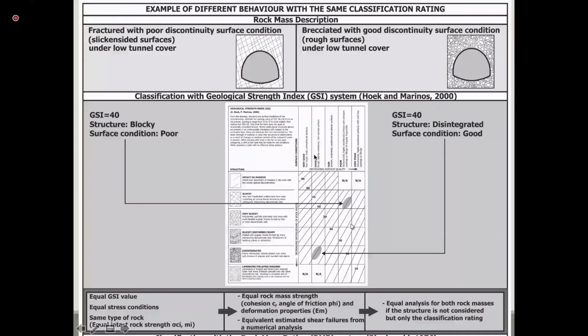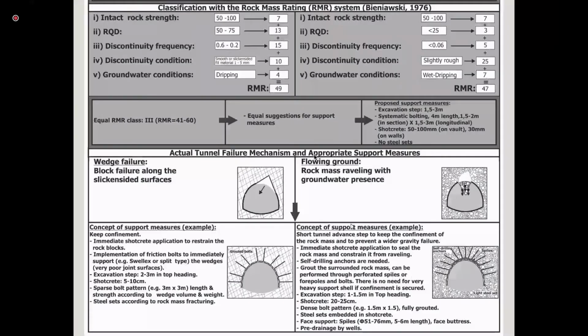If you do that, if you go and calculate your properties by the Hoek and Brown failure criterion, you will find equal rock mass strength, cohesion and angle of friction, and deformation properties, and equivalent estimated shear failures from a numerical analysis. So you will have equal analysis for both rock masses if the structure is not considered, but only the classification rating. And if you do that for the RMR system, again, you will find yourself in the same support category, like here 3, for example. So you will get equal suggestions for support measures.